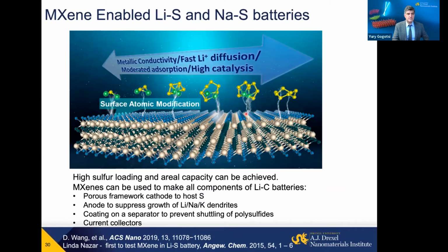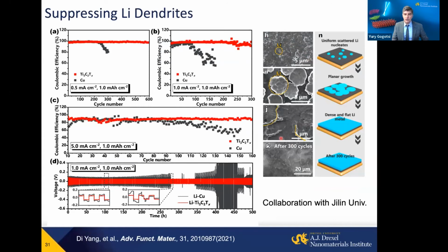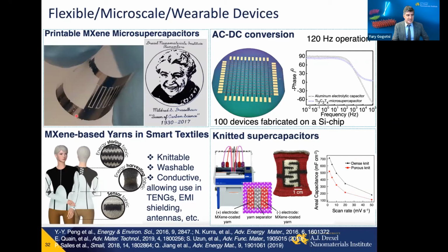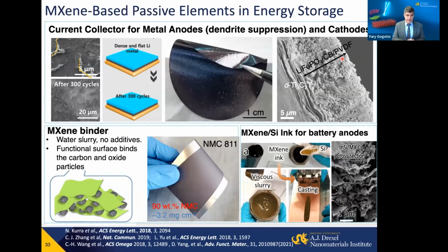But they really can make a difference in metal sulfur batteries, compensating the high conductivity of MXene for low conductivity of sulfur and strongly adsorbing polysulfide. They can suppress dendrite growth, allowing metal batteries, and also act as much thinner current collectors. They can enable flexible devices, printable devices on chip. They can be incorporated into fibers and textiles, helping with developing future flexible, transparent, wearable energy storage, but also by the same token energy harvesting, for example, TENG solutions here, or high frequency applications, again, because of this very high ionic and electronic conductivity here.